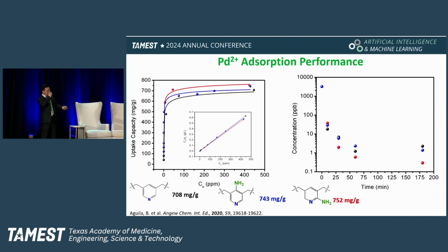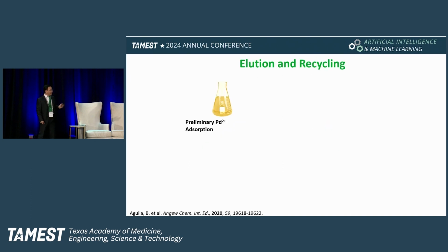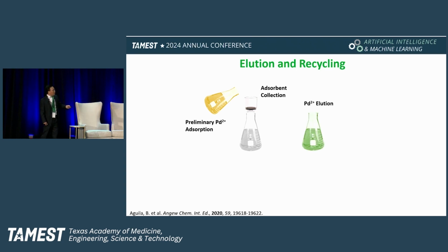And also, we can start from about 10 ppm, and we can reduce to less than 0.1 ppb. That means the recovery efficiency is extremely high. It's 99.99%. We can efficiently recover the precious metal. Of course, this type of material can be easily recycled. We just do a simple filtration, and then we have the solution.